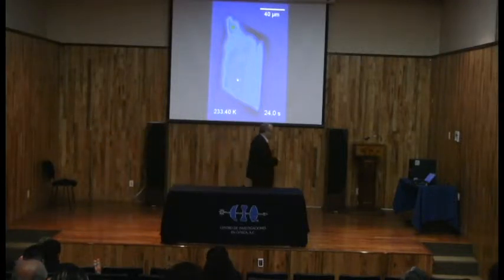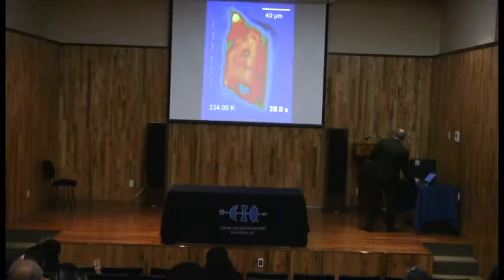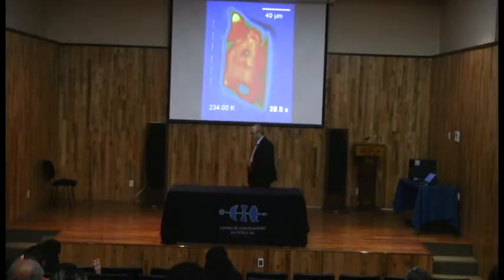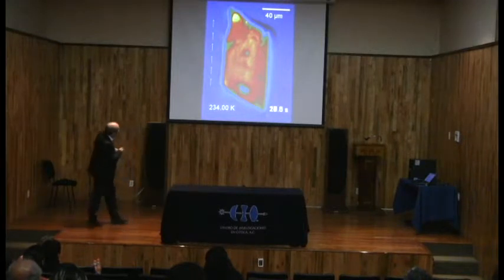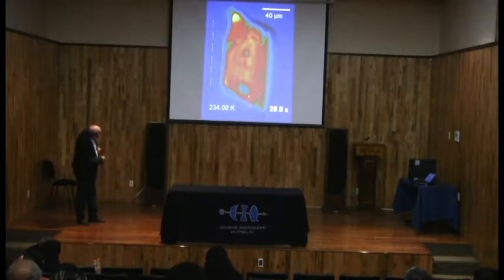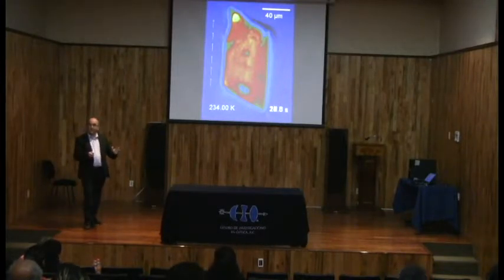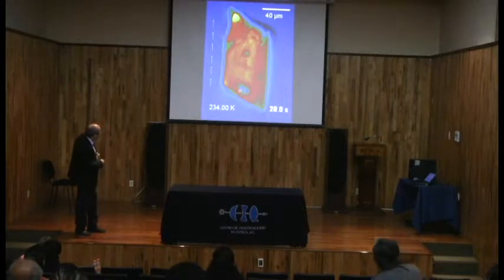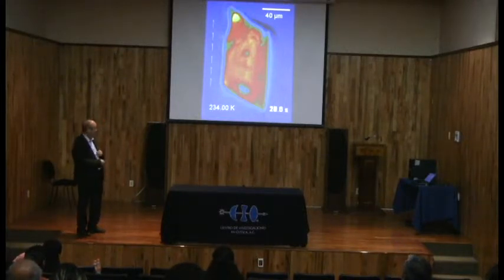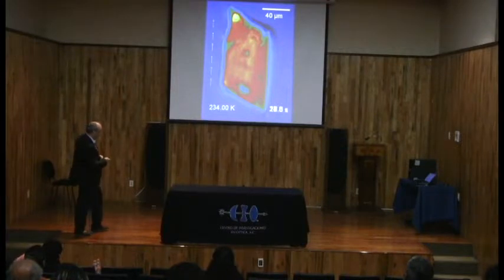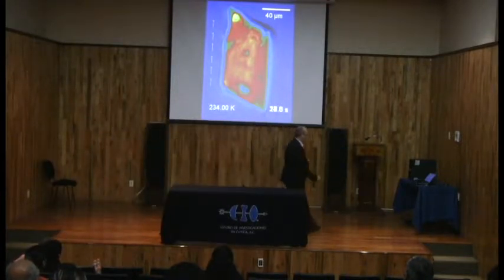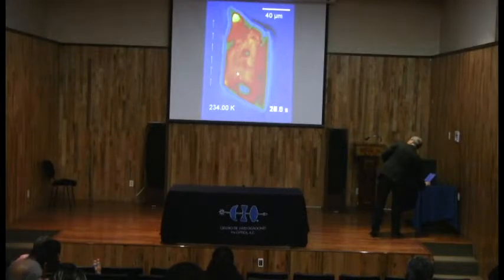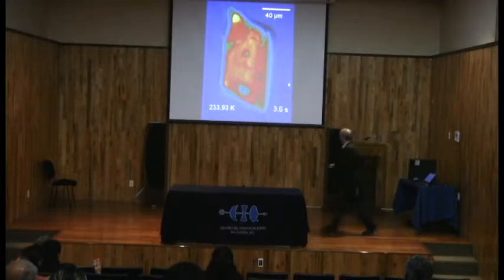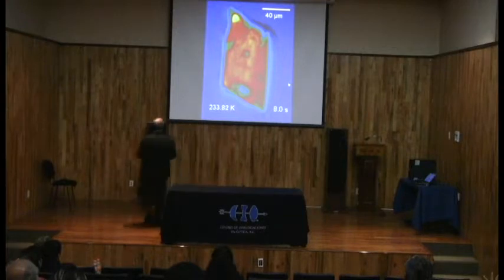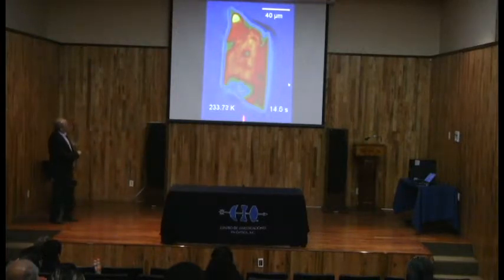So then we used exactly the same crystal in the same condition. You have seen in the previous one that you have the nucleation and growth in this direction here, and this is the crystal, the same crystal. We did exactly the same experiments, but the difference is that we put here a defect by just ablation. Okay? When we do this, we measure the propagation optically. You see that now the nucleation and growth started from the defects and goes in the other directions.